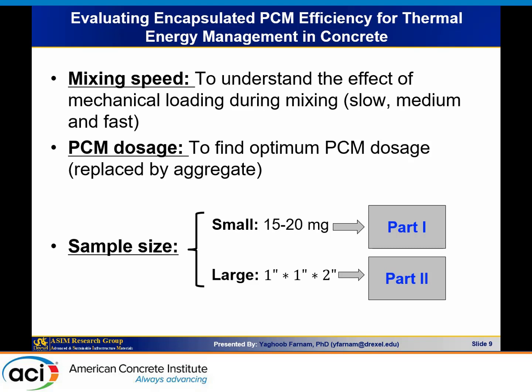One of the things that I want to mention here is that PCM, we just replace it by aggregate. So we take a portion of aggregate, then we add the PCM by volume inside that. So this is the way that we could incorporate PCM. When I say 10% dosage of PCM, I mean that 10% of the aggregate is replaced by volume by PCM.